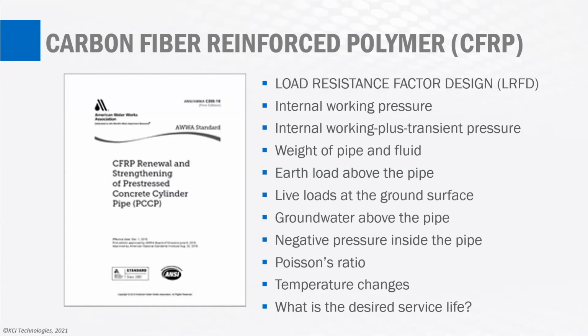In 2018, AWWA published a standard for CFRP renewal and strengthening of PCCP. It's based on an LRFD design methodology, and it looks at a number of different aspects of the long-term service of this lining system. Which includes things such as your internal working pressure, for example, internal working pressure plus transient pressure. What is going to be the result of the weight of the pipe and fluid on this lining system? Earth loads above the pipe, how will that affect the lining?